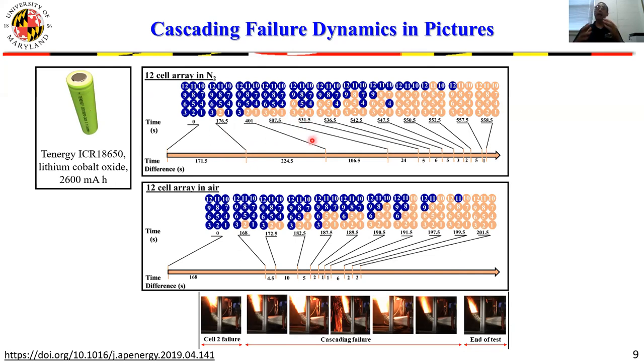It propagated in every single nitrogen test that we conducted. We also found when we examined the air tests, and just for clarity, we performed the tests on multiple arrays, so they were repeated multiple times, that we also didn't need to have any special means to generate flaming combustion inside the tunnel. In fact, we found that the flaming combustion inside the tunnel in the air experiments was so intense that even when we provided the airflow rate at about 3 meters per second into this tunnel, the combustion process consumed pretty much all oxygen that was available.